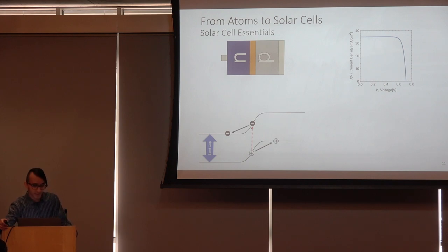Now, when you have a solar cell, the quickest and most direct way of seeing how your solar cell is performing, or at least the most common way, is to take what is called a JV curve, where you essentially subject your solar cell to different voltages. And as you're subjecting it to different voltages, you're going to be able to get different currents for a given sort of illumination. And you get a curve that looks like this if you have a very nice solar cell. Now, if we take that JV curve and multiply it by the voltage again, we get the power density.